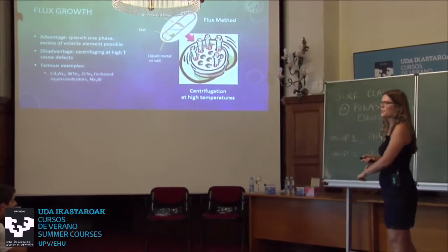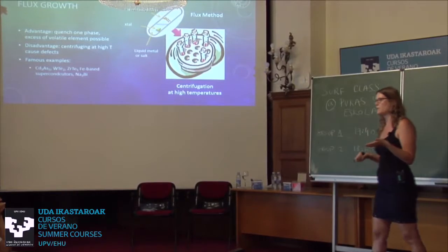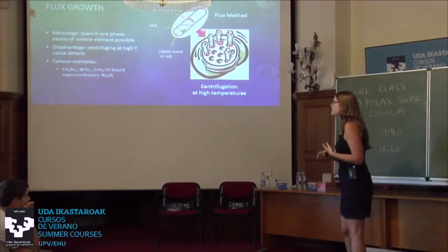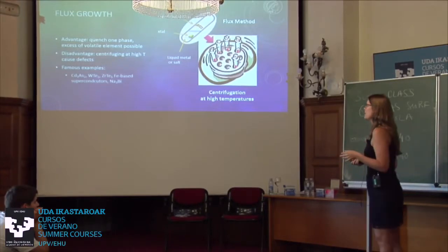The advantage is you have only one temperature because you quench from it. So in a compound like cadmium arsenide, you won't have competing phases. You have an excess of maybe one element, so you don't have defects from having too little of the elements.